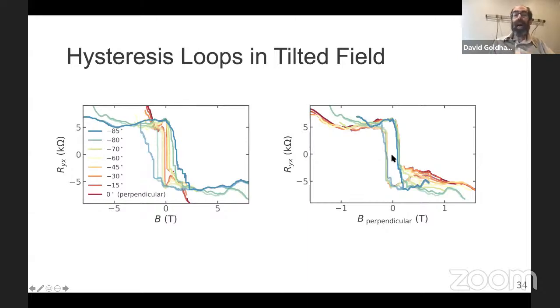So that really tells you that this is a highly anisotropic system. The out-of-plane field matters, and that's what you would expect from little current loops. It's not what you'd expect from spins in graphene.